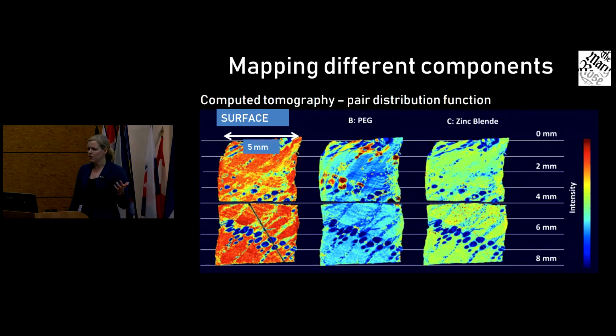So on the right-hand side, we found this nanophase. This matches with a zinc blende, so it's a zinc iron sulfur. You can see that they're not actually near the surface, they're kind of a tier down. So perhaps they did form at the surface and they've been washed out, we're not sure. But this is really powerful at telling us what's there and where it is in the wood. We actually have other phases as well, which we haven't managed to match to anything yet. So this is an ongoing process to understand what we're dealing with.